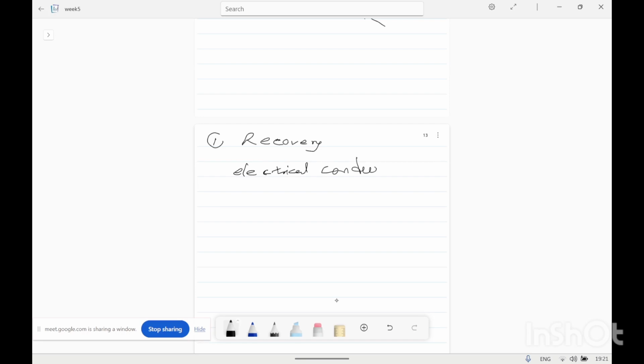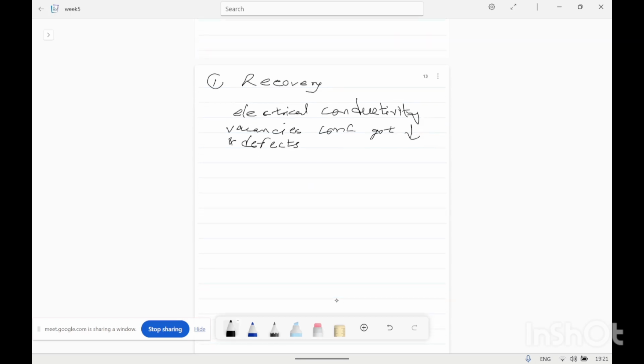So how is the electrical conductivity increased in the annealing process? During recovery, the vacancy concentration decreases, and the vacancies and defects concentration decreases. The decrease in vacancy and defect concentration allows the electrons to move freely without any hindrance, thereby increasing the electrical conductivity. Vacancy defects are point defects.